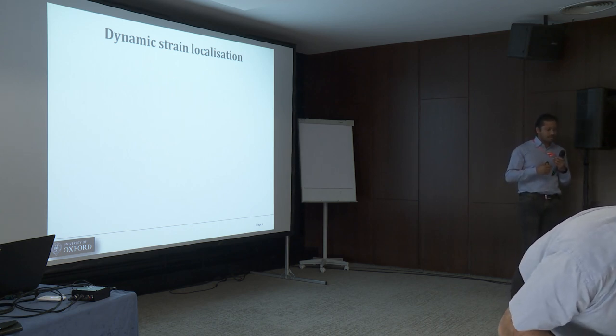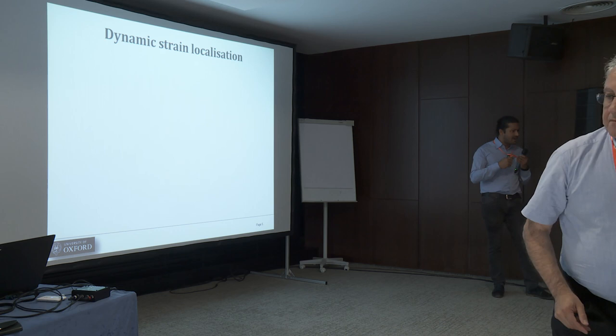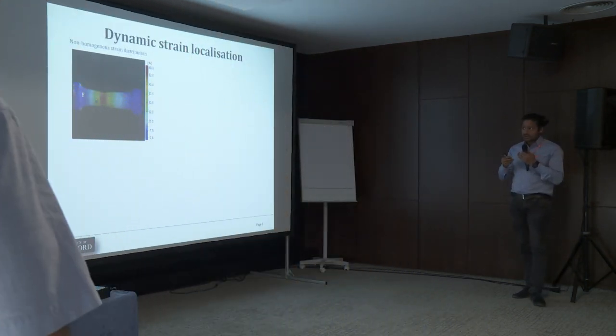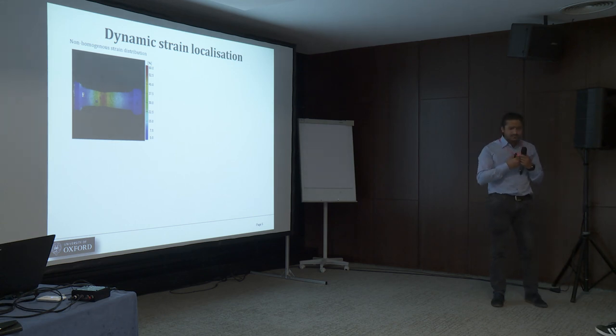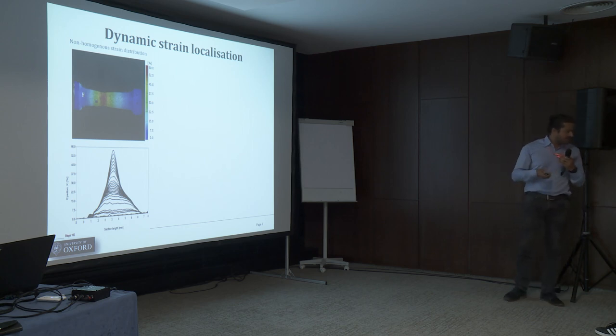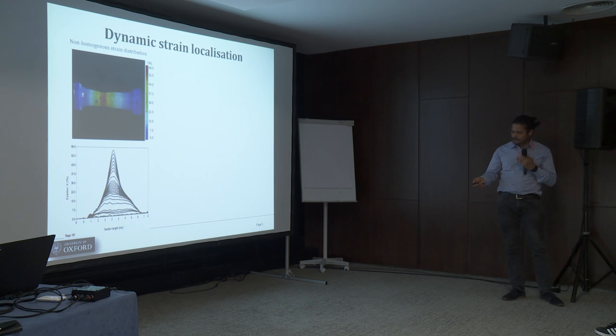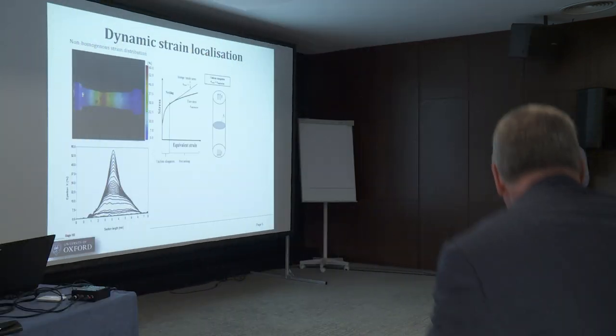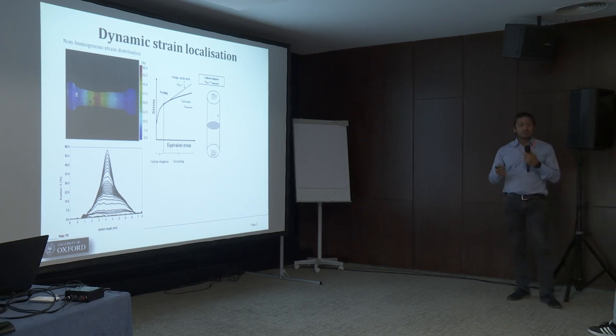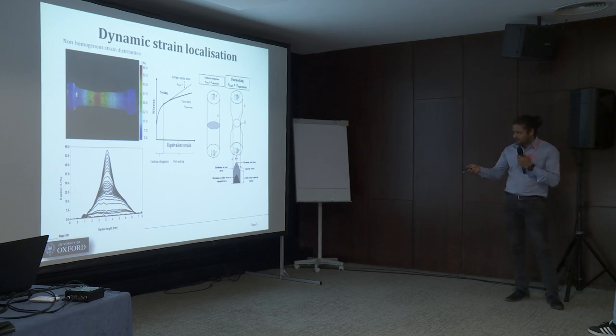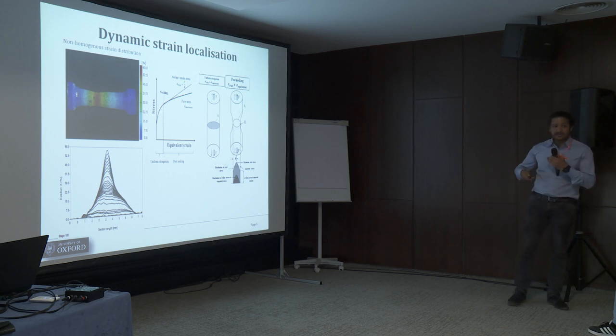In my PhD, I took a goal to understand dynamic strain localization — why and how. Using digital image correlation, we observe that once the material undergoes plastic deformation, strain becomes localized across the cross section, causing non-uniformity in the strain field, as further elaborated in the graph. This affects the escalation of stress and strain: during uniform elongation, the two stresses are equal to the equivalent stresses, but once necking occurs, they are no longer equal because of the role of radial stresses coming into play. That's what we need to address and understand.